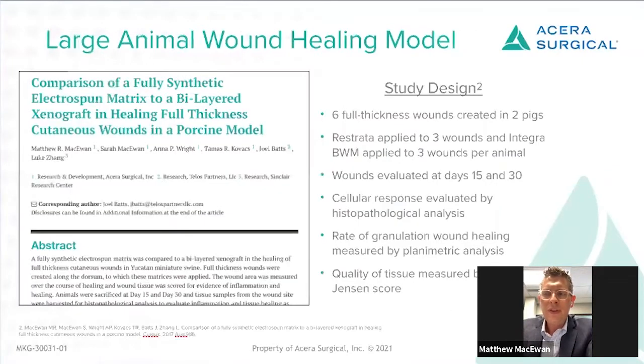And so with that, we took our material, we re-engineered it, and we tested it out in a large animal wound healing model. So we created full thickness wounds in the back of pigs, essentially creating wounds that went all the way down to muscle fascia. We then treated those wounds with either our electrospun materials or some of the existing matrices that were presently used in the wound healing setting, particularly in this case, Integra's bilayer wound matrix product. And the results were pretty interesting.